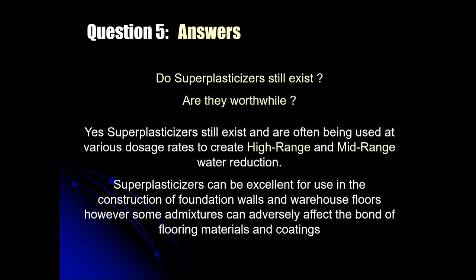Do superplasticizers exist, and are they worthwhile? Yes, absolutely. Superplasticizers still exist, and they are used. And depending on the dosage, there used to be two classes. We used to say mid-range and high-range, but a lot of times it's just a matter of dosage of a high-range to create a mid-range. They can be absolutely excellent for industrial slabs that don't have floor coverings or coatings.